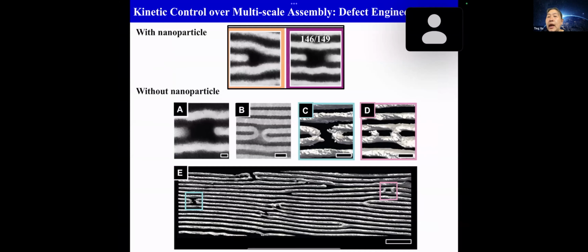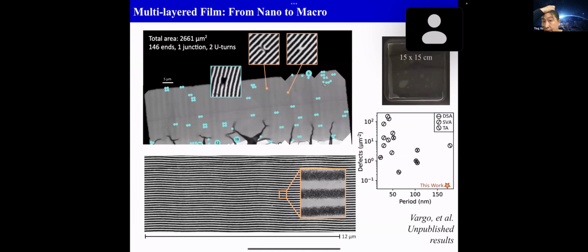So with this, I'm just going to pass over this because of time. Because you understand the pathway, you are in a position to be able to control the defect type, because the growth process as well as the local chain reorganization at the defect site is going to affect what defect type you have. And that is quite important for the application, even though it hasn't really been investigated for nanomaterials beyond direct self-assembly. So once you have these numbers, you just have to put it into application.